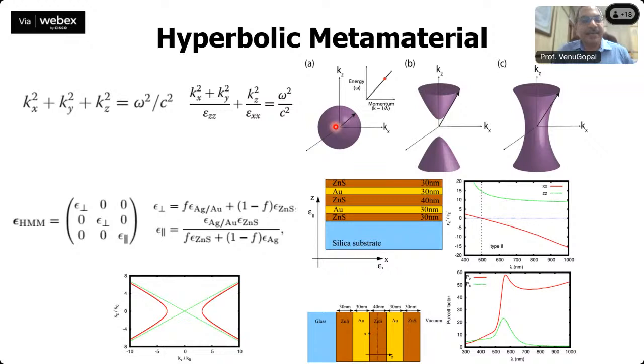Right. So from the effective medium theory, we can get, for alternating layers of dielectric, zinc sulfide in this case, and gold as the metal, a stack of these, and we can get epsilon perpendicular and epsilon parallel. And by choosing the ratios and dimensions properly, we can get, for example, epsilon xx going negative below, say, 500 nanometer, and epsilon zz positive. Right? So the zz direction is insulating or dielectric, and epsilon xx is metallic in response.